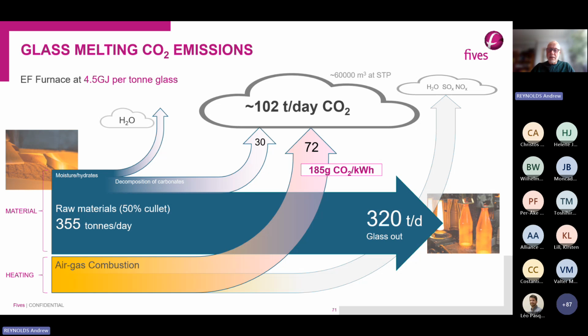So just looking at the melting process, in an end-fired regenerative furnace, if we want 320 tons per day of material coming out of the furnace, we have to put about 355 tons of material into the unit. That's even with a 50% cullet rate, that's a 50% recycling of glass. We also use carbonates in the raw materials, and those carbonates decompose and produce CO2. So 30 tons of that 355 tons will be lost as what we call process melting CO2.